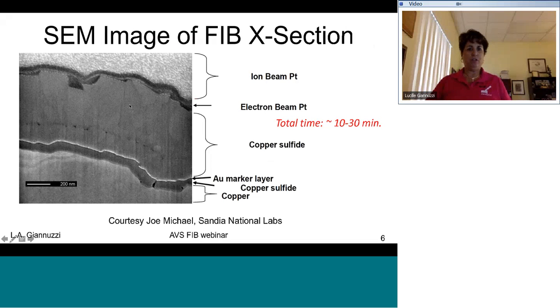And here's an example of the SEM image of a FIB cross-section, courtesy of Joe Michael. So here you can see this somewhat rough surface, which again is evened out a bit by the platinum. You can see also this is E-beam platinum on top because you didn't want to damage what you were looking at right at the top surface. Copper sulfide, gold marker, another copper sulfide, copper. You see these different layers. The total time should be anywhere between 10 and 30 minutes to make one of these SEM type samples. It should be pretty quick. Okay.